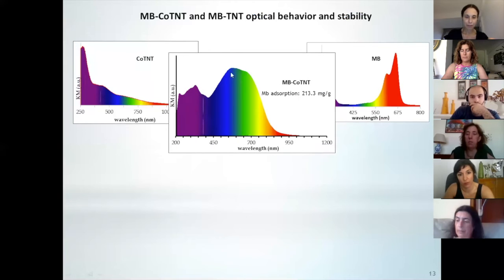So this is the optical spectra that we have. Of course, we have absorption of the dye. And as you can see here, the absorption of the dye is very high under this condition. And it's much higher than the one that we have for the pristine titanate nanotubes.